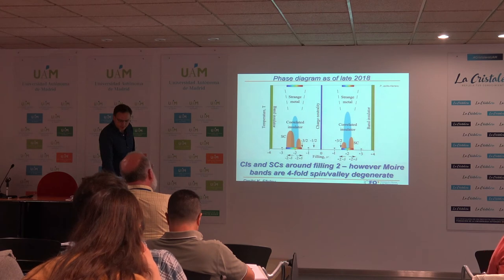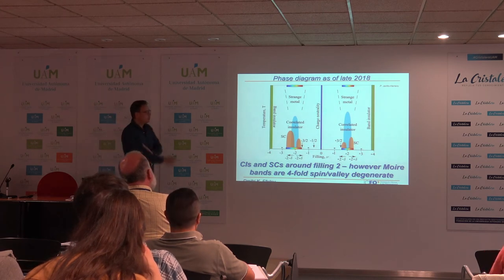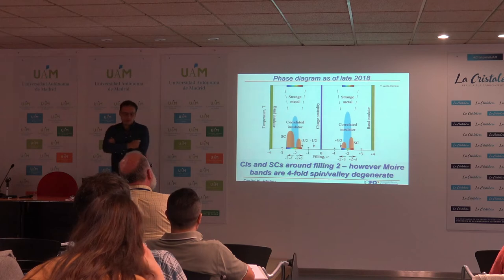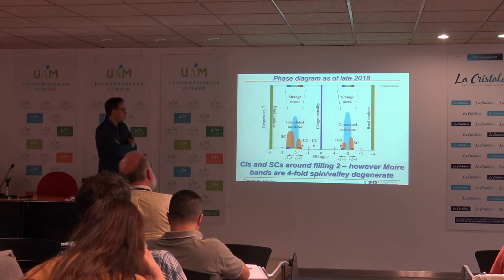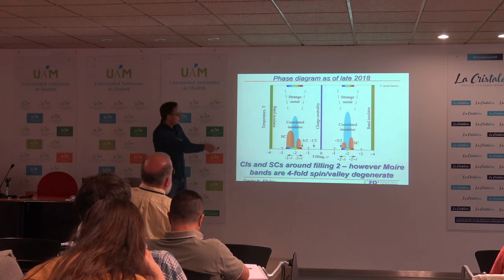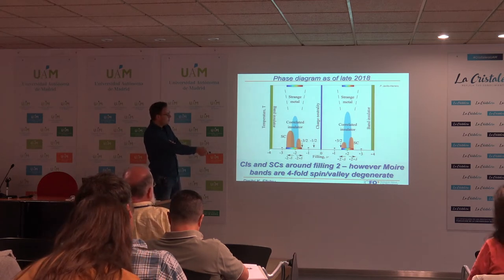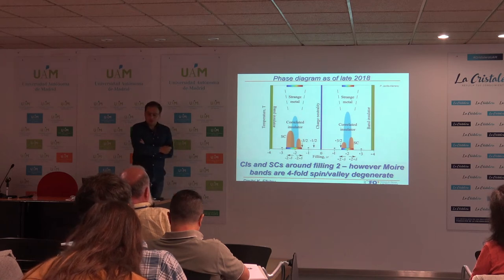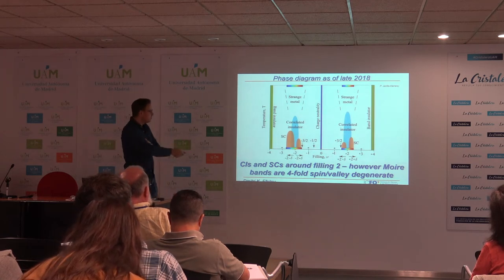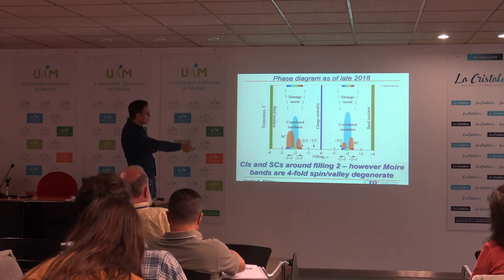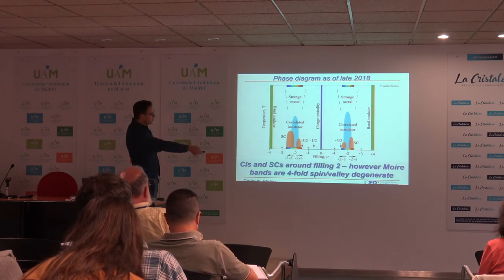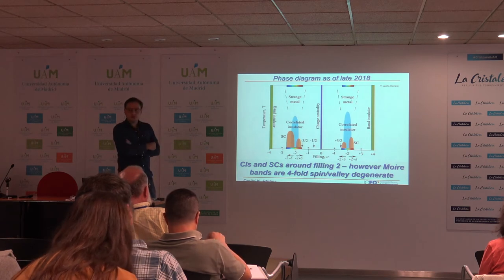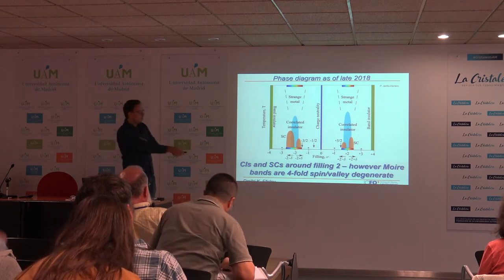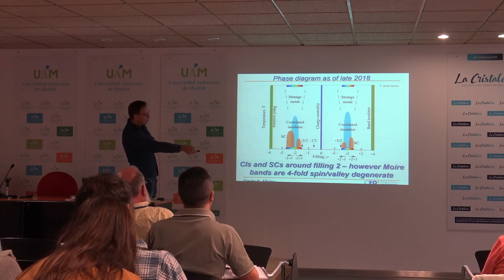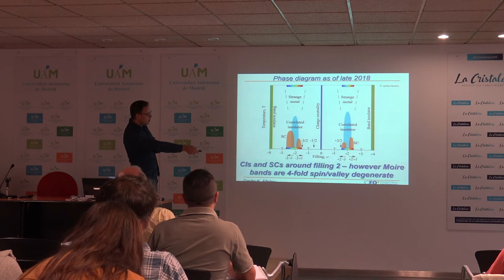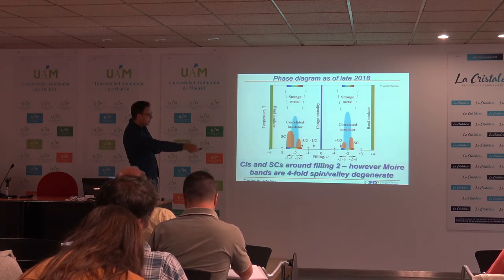And this is basically the phase diagram which is used by Pablo these days. So this is the phase diagram where really as we go to the edges of the moire band, if we are basically at minus 4 electrons per unit cell where the moire bands are entirely empty, we're getting this band insulator which is marked by a high resistance. Then at zero filling, we get the charge neutrality point, which is also a highly resistive state. Then we completely fill up the energy band with plus 4 electrons. We again get a band insulator.